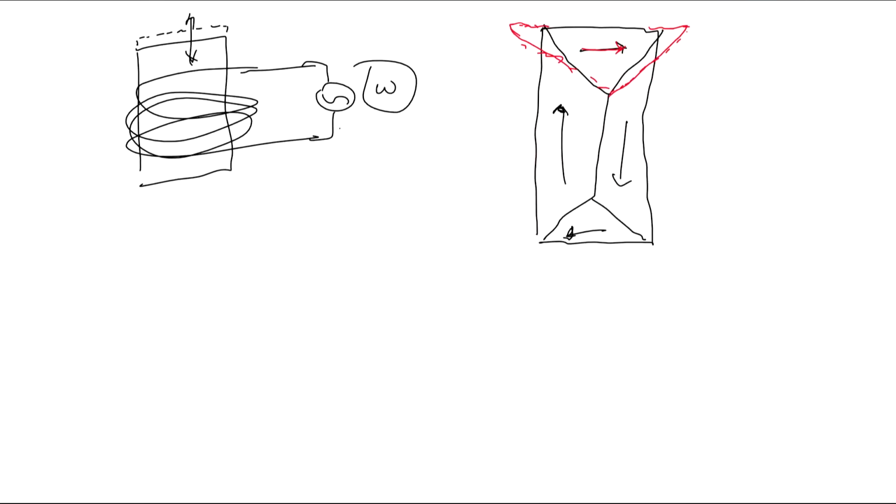But at the same time, if we take this domain, it is magnetized that way, so that domain wants to be bigger in this direction. And therefore there would be a certain strain induced in the material. So at all these boundaries between domains, there would be a certain strain related to magnetostriction.